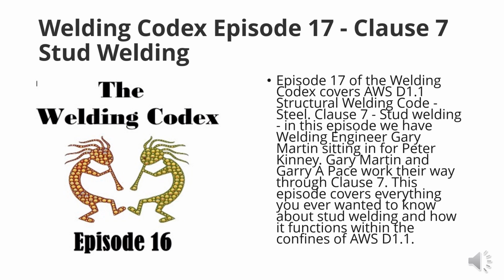9.5.5.2, stud materials shall meet the following requirements. And this is, again, under the fillet welding option. Studs meeting the requirements of 9.2.6 or 7.2.6 shall be acceptable for use in prequalified WPSs. So that's just saying, as long as you get the prescribed material at the beginning of this chapter, you can use a prequalified WPS for it. Prequalification does not like using unspecified steels that aren't found in the code. That would throw you into a full qualification.